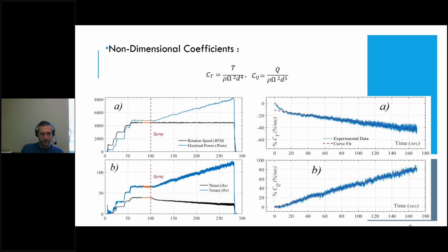And you can also see the torque increase and important thrust decrease during the icing events. And then at some point there's going to be a shedding of the ice on one or more blades, and then the vibration levels will increase due to the imbalance, and we will attain vibration above the safety limits given by the manufacturer. So we have to stop the test at that point. And we use also for the analysis non-dimensional coefficients, so the thrust coefficient and the torque coefficient. And you can see during the test in real time the percentage of thrust coefficient losses and torque coefficient increases.